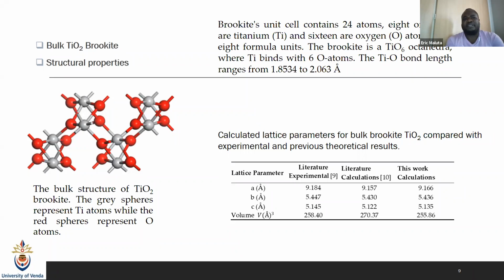But the issue is, because I've said we have chosen the Brookite unit, it's just a unit cell of 24 atoms, where we have 8 titanium and 16 oxygen, because normally we have 1 titanium to 2 oxygen. And then it's just an octahedral where the Ti atom binds to 6 atoms, and their bond length ranges from 1.8 to 2.05 angstrom.